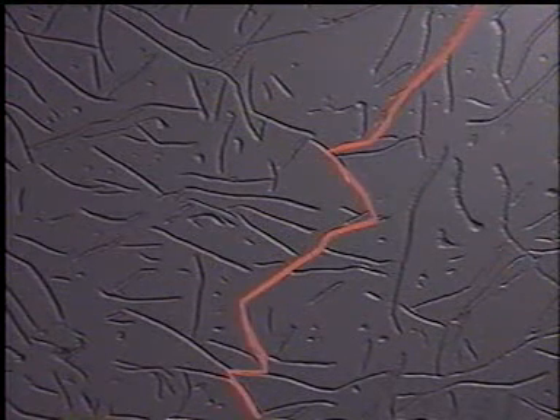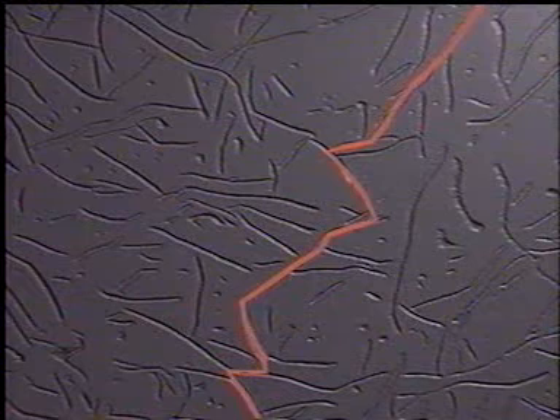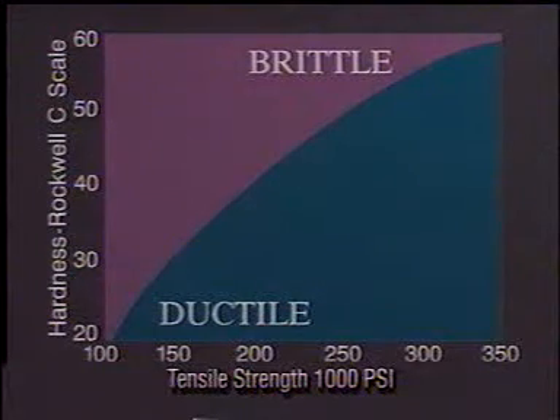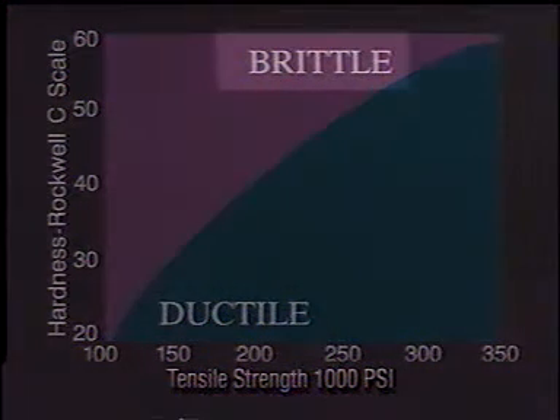These notches are in the form of very thin graphite flakes. And according to the indicators, notches indicate a trend toward brittle behavior. In reality, the notches override the strength and hardness factors. Hence, cast iron with low strength and hardness appears to fracture in a brittle manner. On a microscopic scale, however, gray cast iron still behaves in a ductile manner between the graphite flakes.